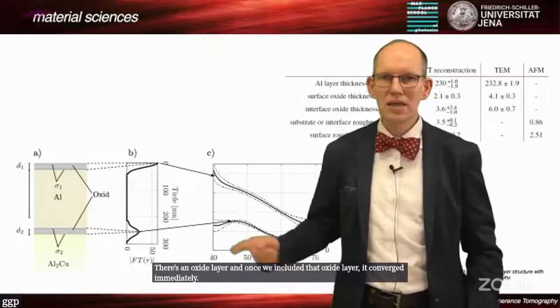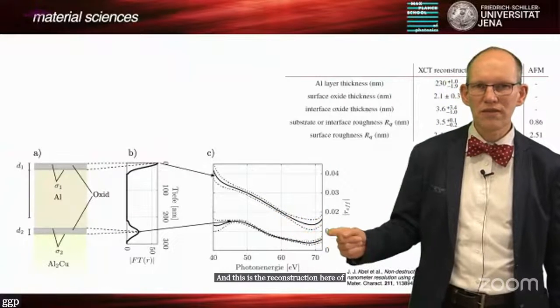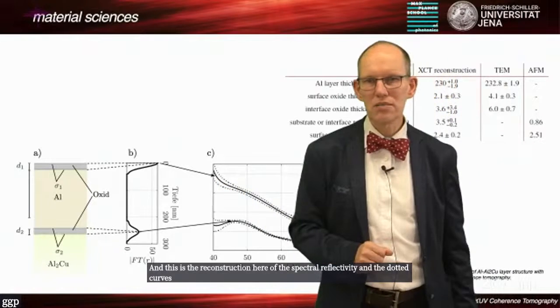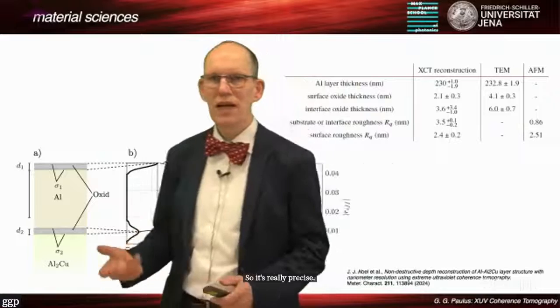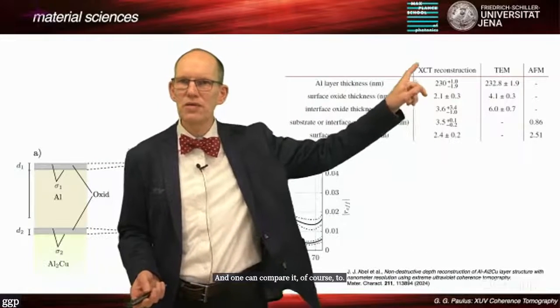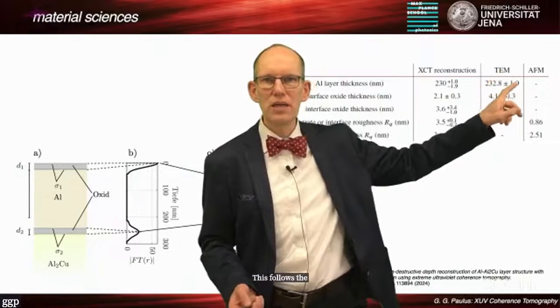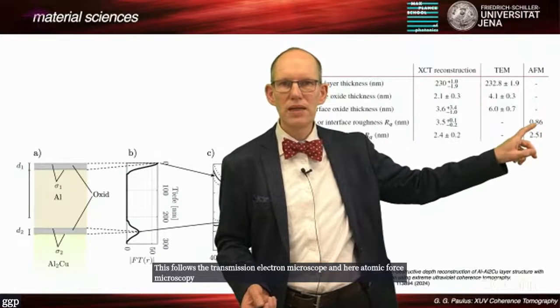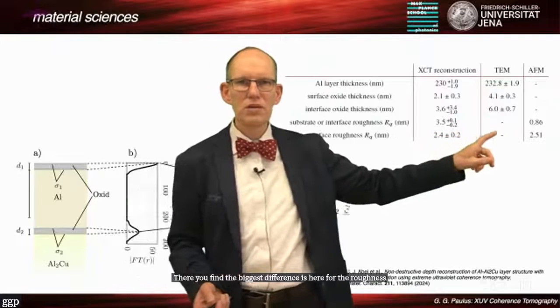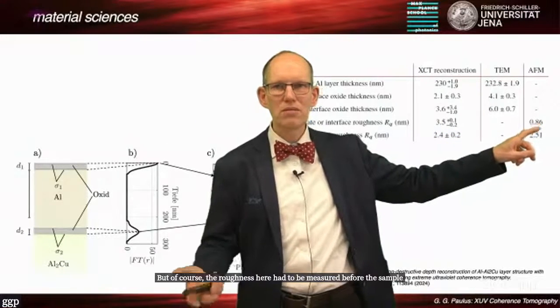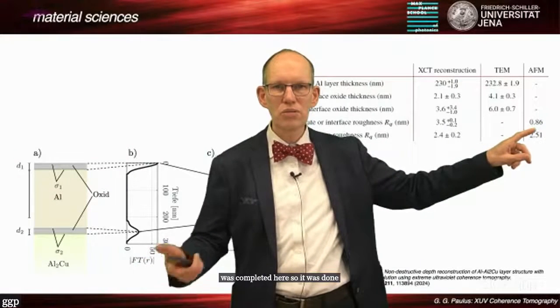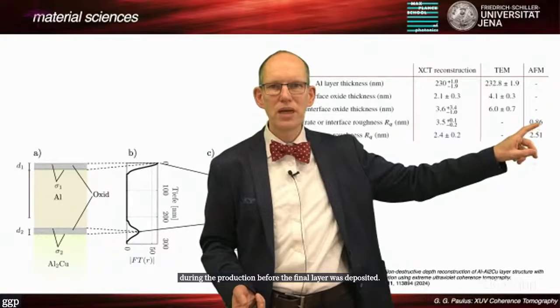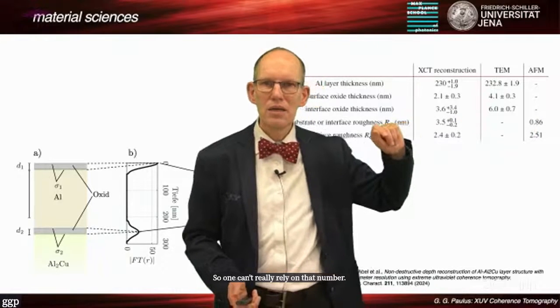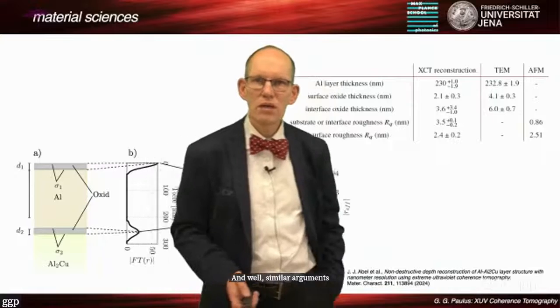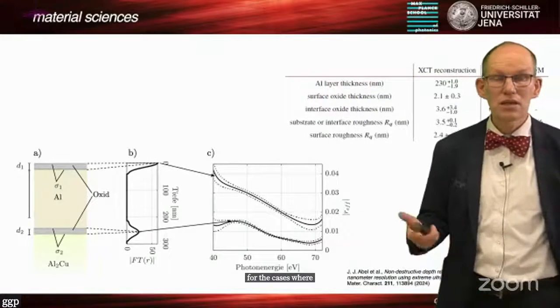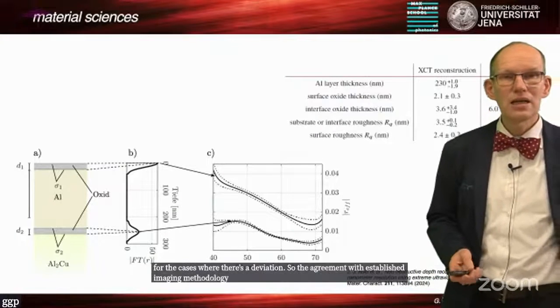Right, and this is the reconstruction here of the spectral reflectivity, and the dotted curves are the error margins. So it's really precise, and one can compare it, of course, to these numbers for XCT, this for the transmission electron microscope, and here atomic force microscopy. There you find the biggest differences for the roughness. But of course, the roughness here had to be measured before the sample was completed. So it was done during the production, before the final layer was deposited. So one can't really rely on that number. And similar arguments for the other cases where there's a deviation. So the agreement with established imaging methodology is actually very high.